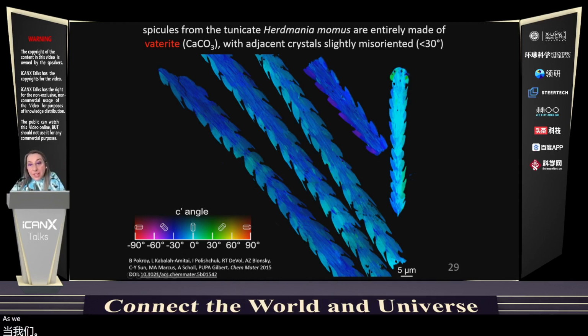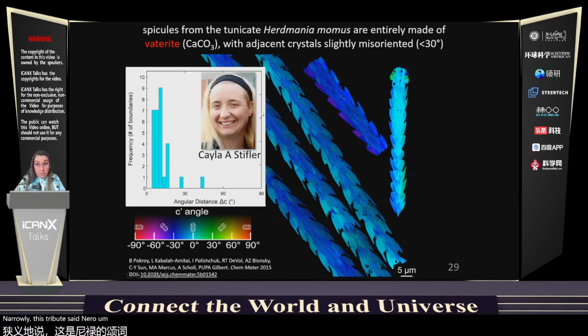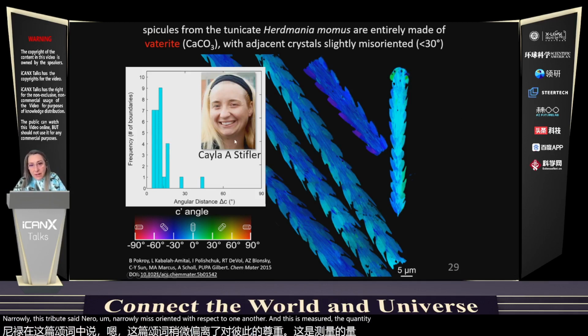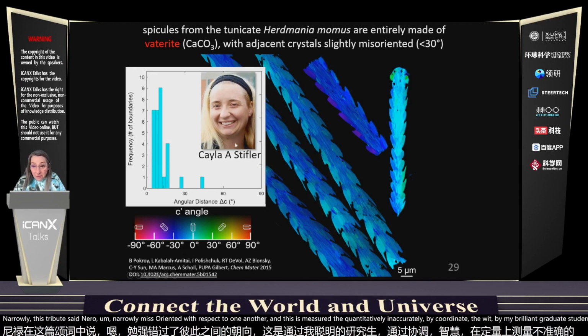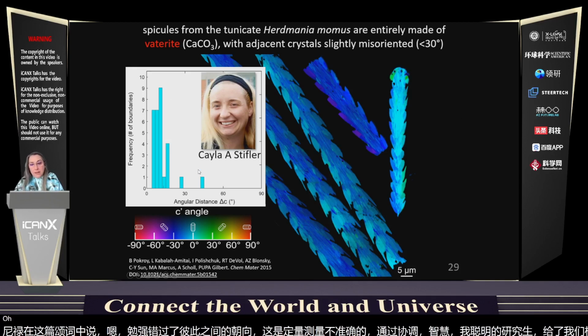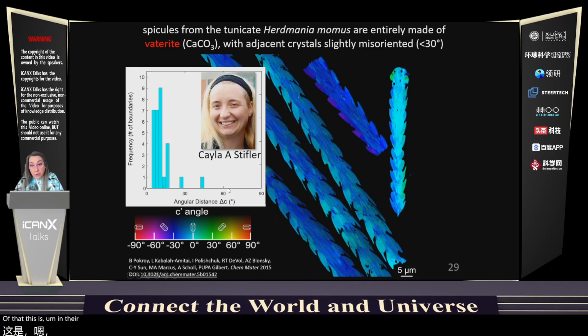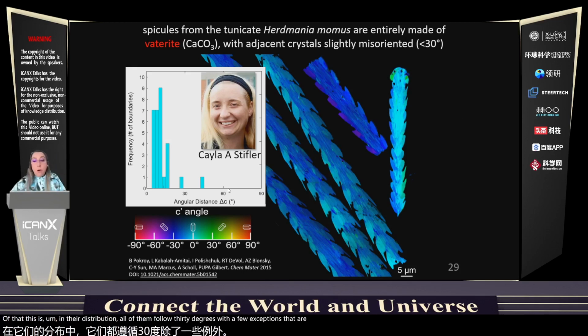We find that the adjacent crystals are also narrowly distributed, narrowly misoriented with respect to one another. And this is measured quantitatively and accurately by coding by my brilliant graduate student, Kayla Stifler. And we find that this is a narrow distribution, all of them below 30 degrees, with a few exceptions. There are a few outliers, but by and large, it's a small misorientation angle of adjacent